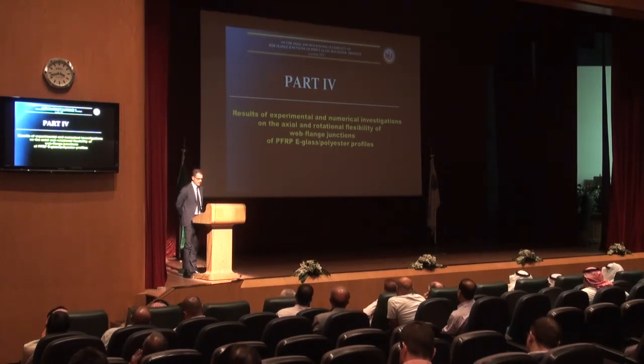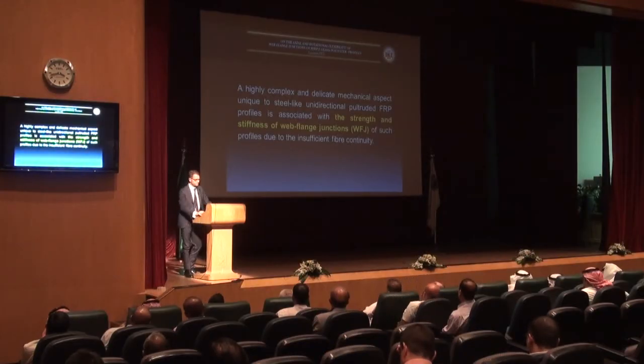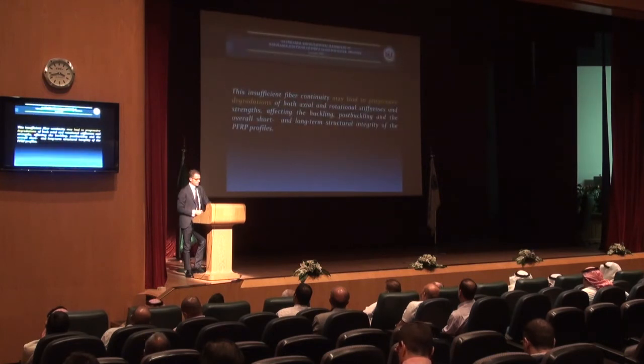on a very important aspect, which is the axial and rotational flexibility of the junction between the web and the flange of these materials. A highly complex and delicate aspect, unique to steel-like unidirectional pultruded profiles, is associated with the strength and the stiffness of the junction between the web and the flange. Insufficient fiber continuity in this junction may lead to progressive degradation of both the axial and rotational stiffness, affecting the buckling, post-buckling, and the overall short and long-term structural integrity of the profile.